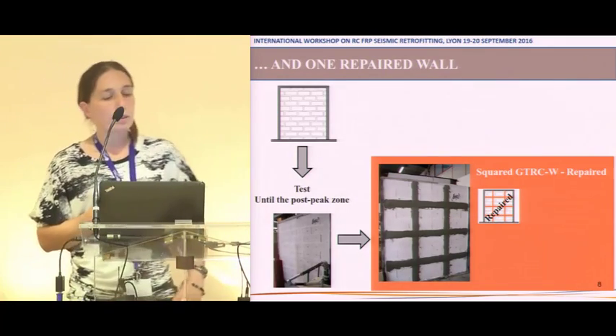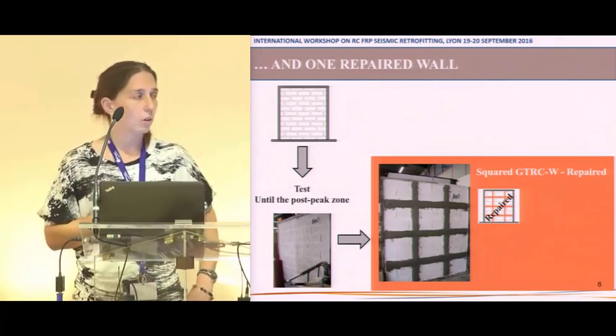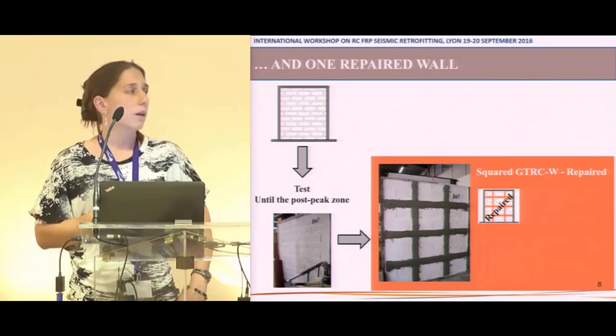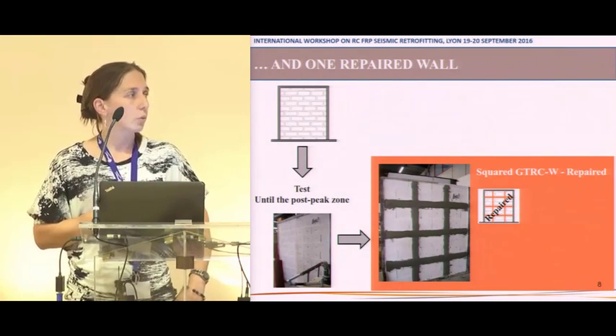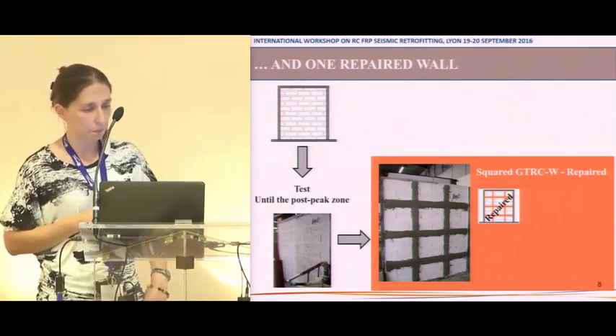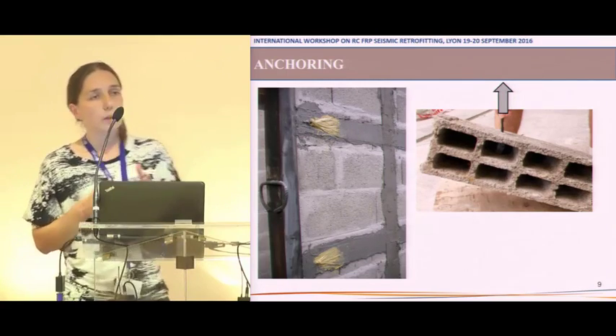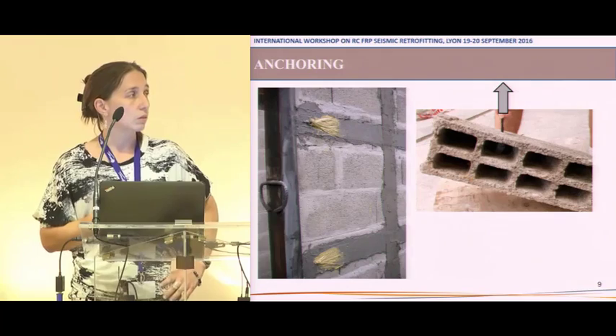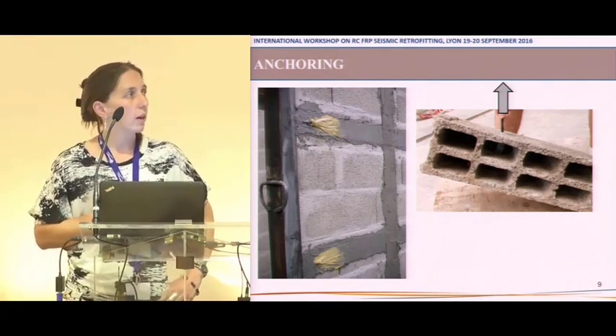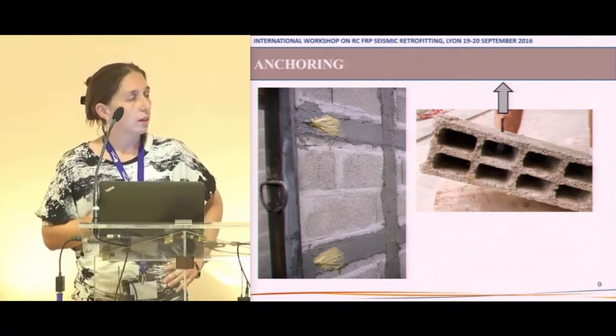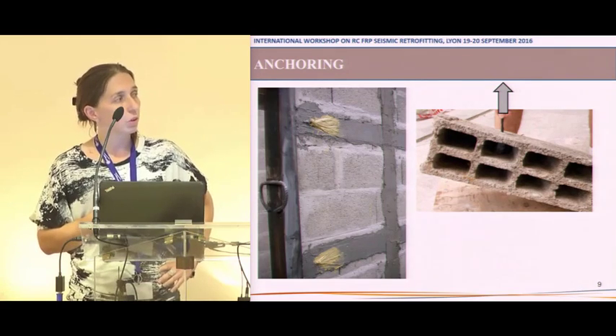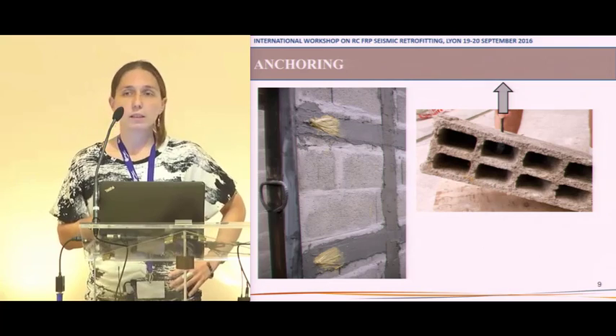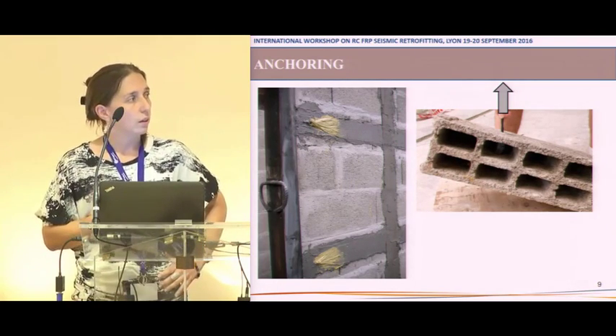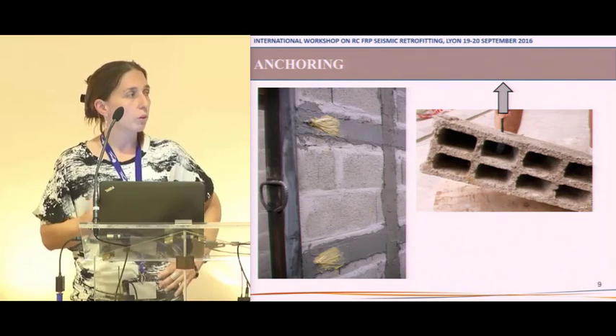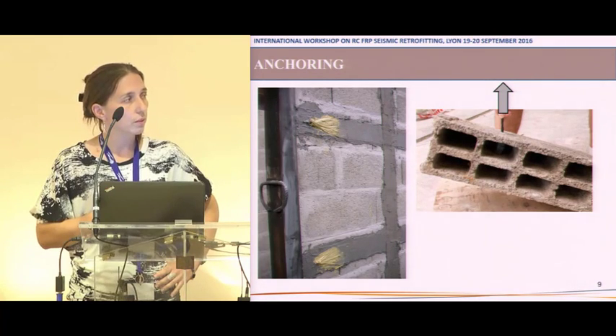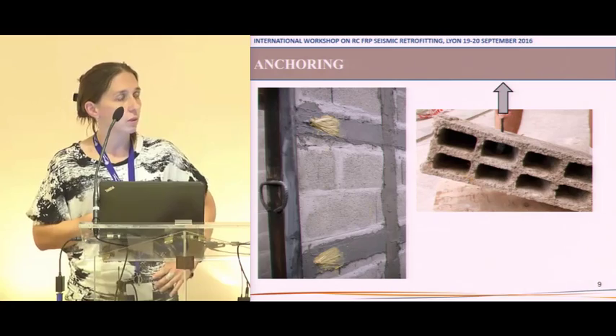In fact, the unreinforced wall has not been tested until failure. We have stopped the test when we have achieved the post-peak zone, and we have decided to repair it afterwards with the squared configuration and with the TRC material. To prevent a potential uncoupling between masonry and textile strengthening bands, an anchorage has been created at the ends of each strengthening band, and this anchor consists of unidirectional carbon mesh sleeves which are embedded in chemical grouting products in order to provide a secure anchoring point. We have decided to introduce the sleeves until the second vertical surface of the blocks.